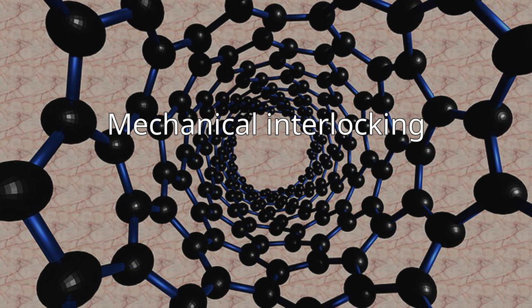Mechanical interlocking. A particular case of non-covalent modification is the formation of rotaxane-like mechanically interlocked derivatives of single-walled nanotubes, SWNTs. In this strategy, the SWNTs are encapsulated by molecular macrocycles, which are either formed around them by macrocyclization or pre-formed and threaded at a later stage. In mechanically interlocked nanotubes, the SWNT and organic macrocycle are linked by means of their topology through a mechanical bond. Combining the stability of the covalent strategies, at least one covalent bond must be broken to separate SWNT and macrocycles, with the structural integrity of the classic non-covalent strategies.